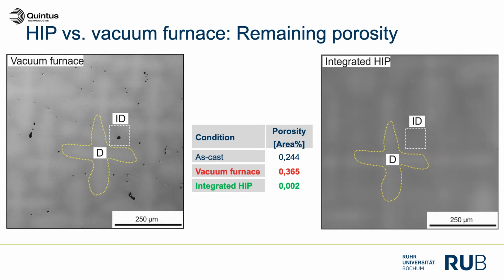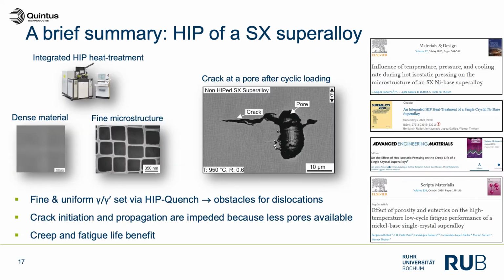In addition, we have no porosity in the material, and this makes crack initiation and propagation very difficult, and therefore also the material's or the component's lifetime can be improved. So there are two very beneficial effects of an integrated HIP heat treatment. You save time and costs, but also you get improved microstructures, no porosity, and a uniform and fine gamma-gamma prime microstructure. So this integrated HIP and heat treatment route gives one the opportunity to cut lead time, potentially cut cost, and also end up with a more ideal microstructure that lends itself to improved mechanical properties.